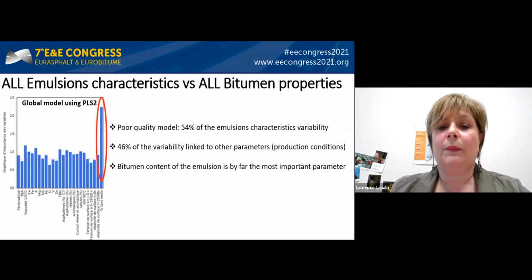We have also used a PLS model to represent all the emulsion characteristics versus all the bitumen properties. In this case, you can see that the quality of the model is poor. Only 54% of the emulsion's characteristic variability is linked to the bitumen variables. The other 46% of the variability of the emulsion properties are linked to other parameters, such as the experimental conditions of the emulsion manufacturing. And the bitumen content of the emulsion is by far the most important parameter impacting the